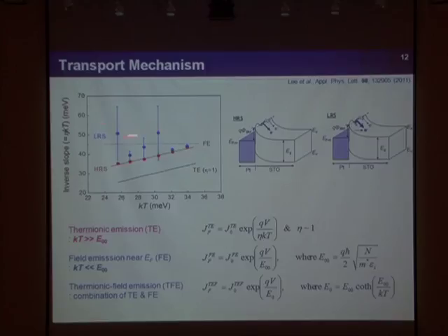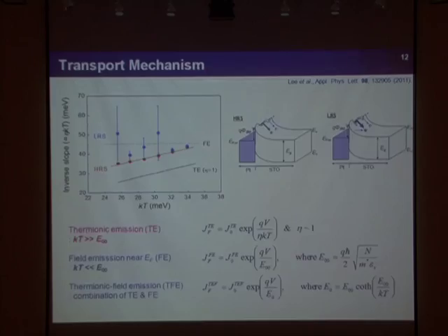Here we can learn that the LRS state doesn't follow thermionic emission behavior, while HRS looks more like thermionic emission. This means that in the previous slide, I estimated the barrier height based on the simple Schottky diode equation, which is derived from thermionic emission theory. So the barrier height taken from that analysis has no meaning at all, because tunneling is involved—we cannot estimate the barrier height that way.